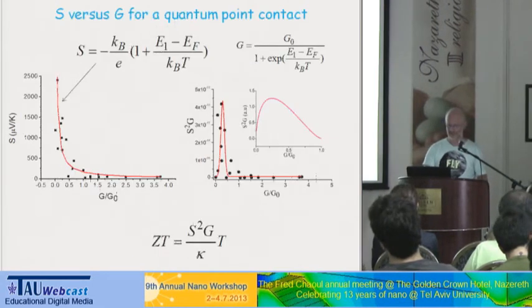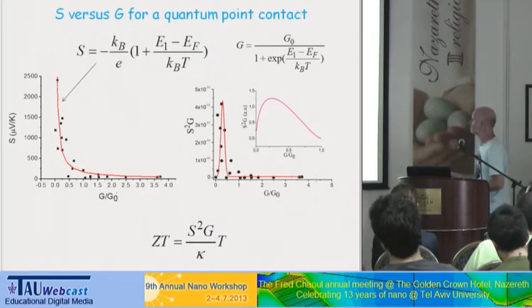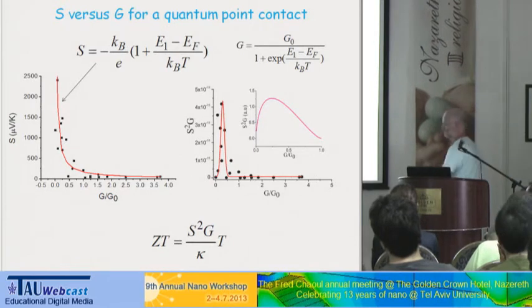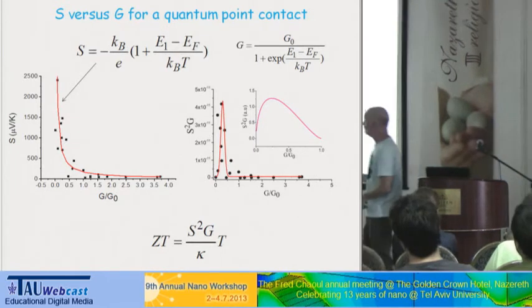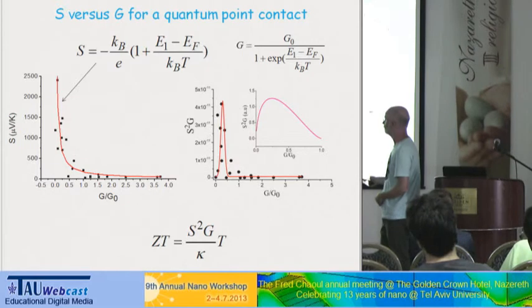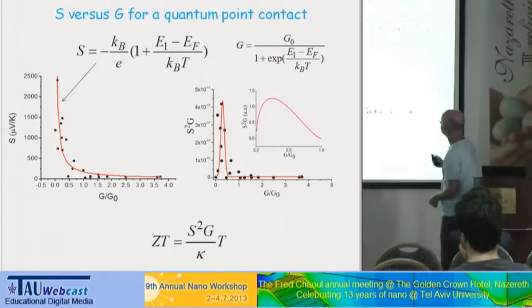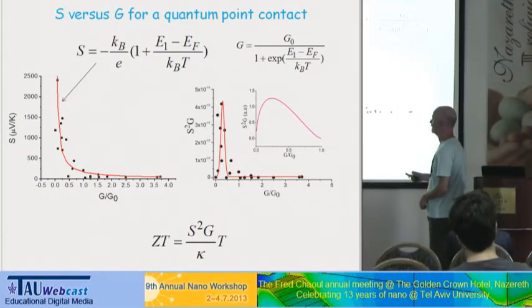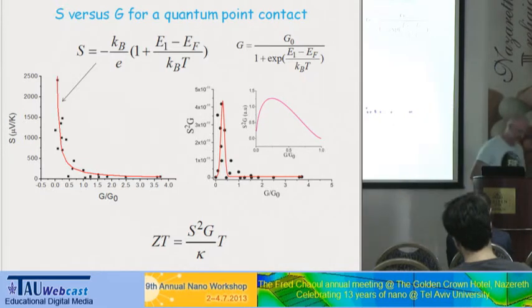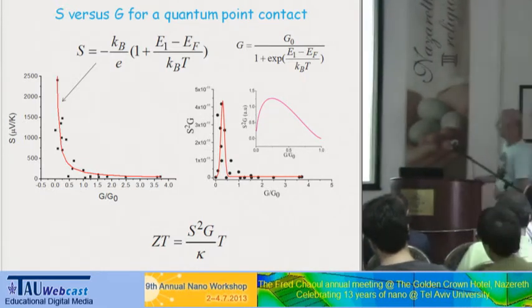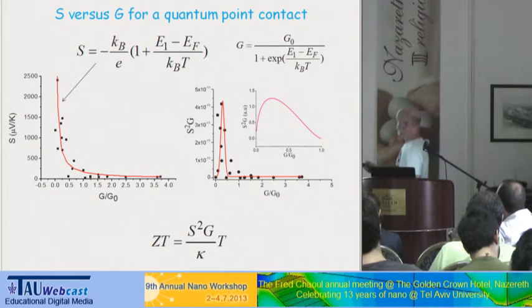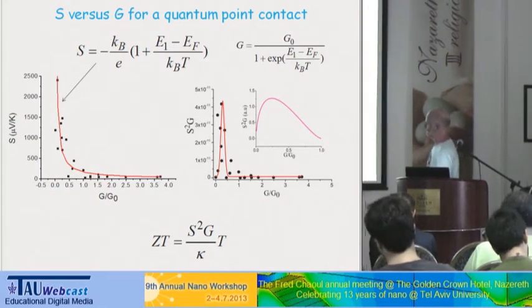So once we have this, we can actually plot. We can make several junctions like this, and then we plot the Seebeck as a function of G. And if you look at the mathematics, you expect to see S as a function of G going like 1 over G, and the red curve that you see here is the theoretical fitting, which is quite good.